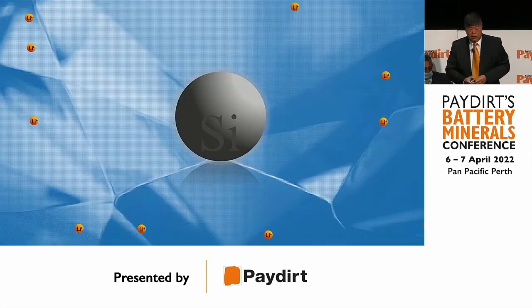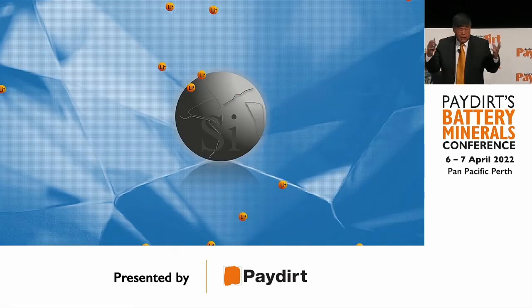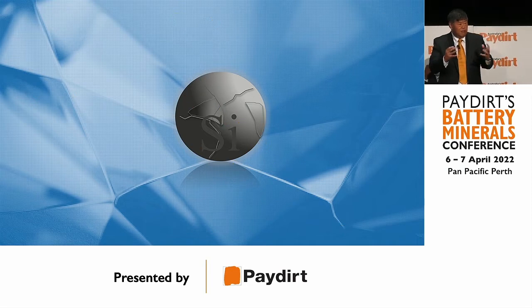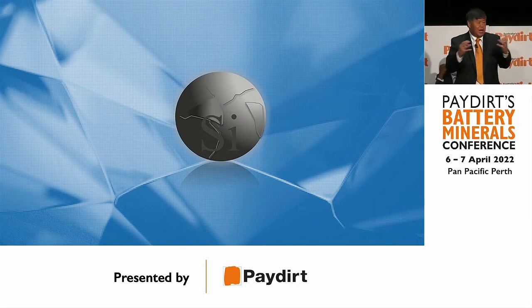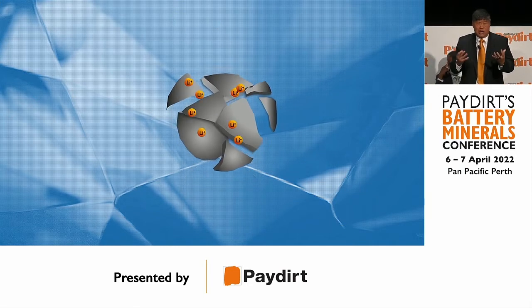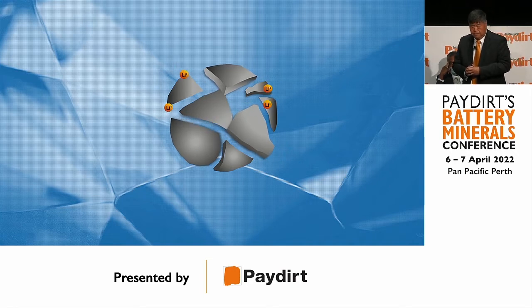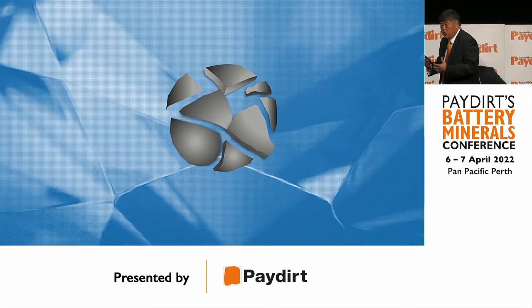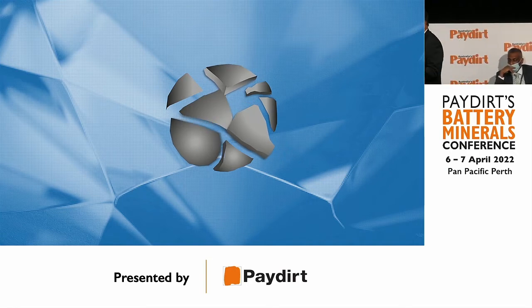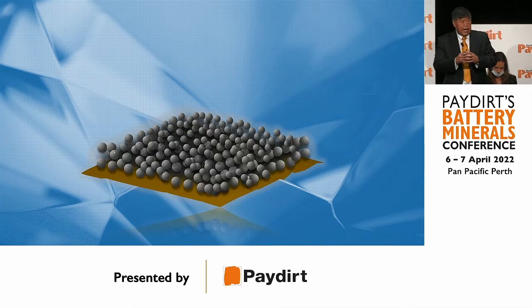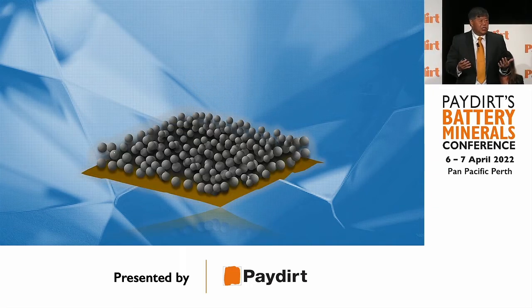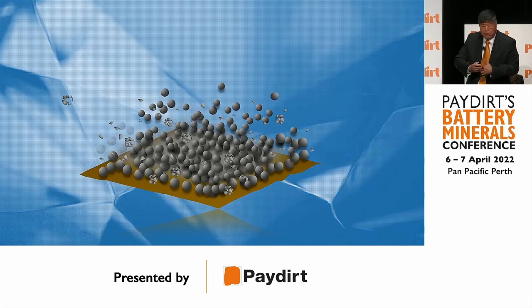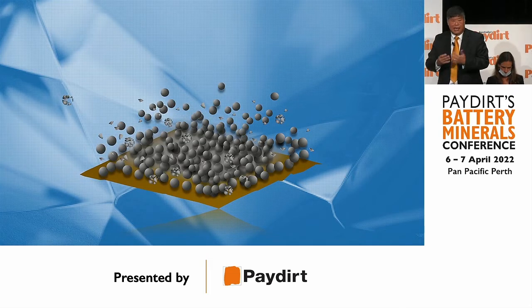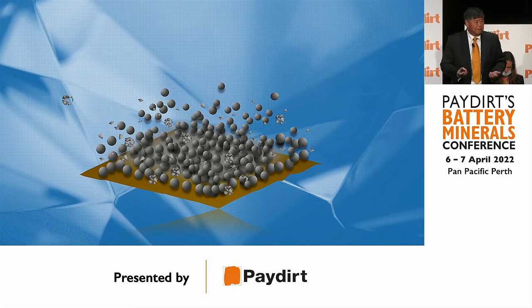So the industry has been trying to resolve this problem. As I mentioned, this expansion of the silicon particle by 300% in volume, and it actually fractures. Now, what happens is when you have the silicon particle in the anode component and it fractures, you get delamination. So the material comes away from the copper collector and you get swelling in the battery. That's a big problem.